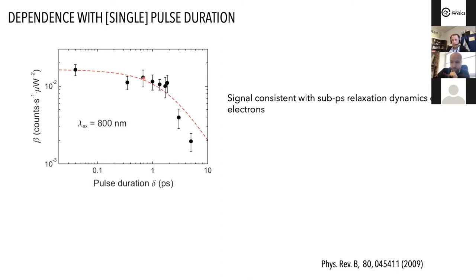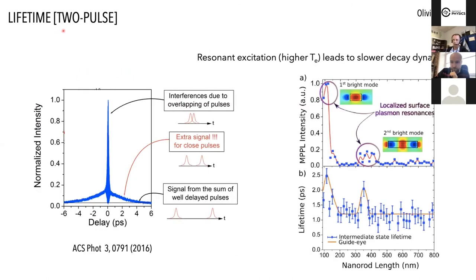Okay, so 1 picosecond is a typical relaxation time for electron-phonon scattering. Slightly faster, maybe 500 femtoseconds depending on the system, but this is definitely consistent with the ultrafast relaxation dynamics of the electrons. So you don't gain too much by making a shorter pulse duration. You have more intensity, you will probably have a lower damage threshold, but in terms of optimum, you'd better hit a pulse duration that is close to the electron-phonon relaxation time in order to maximize efficiency. The other thing that was also interesting in this context is the lifetime that has been measured with a two-pulse experiment. So this is my colleague, Olivier.